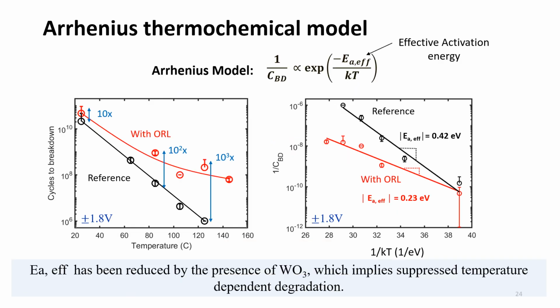Next, we fed the cycles to breakdown versus temperature data into the Arrhenius model to get the effective activation energy. The smaller the activation energy is, the smaller is the temperature dependent breakdown of the device. So we plotted inverse cycles to breakdown with respect to 1 by kT, and the slope of the fitted line is the effective activation energy. You can see that the activation energy of the ORL device is smaller compared to the reference device, which means the temperature dependent breakdown has been suppressed in the ORL device due to the presence of tungsten oxide.